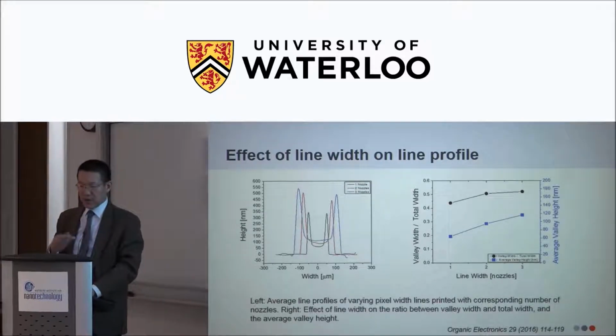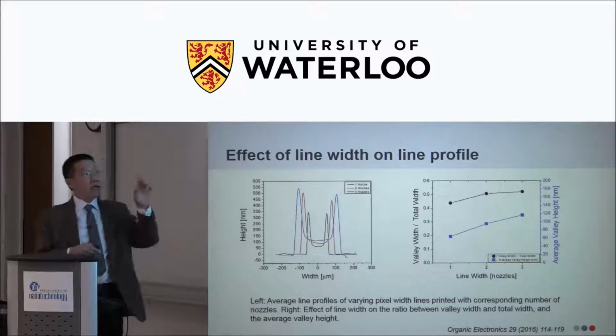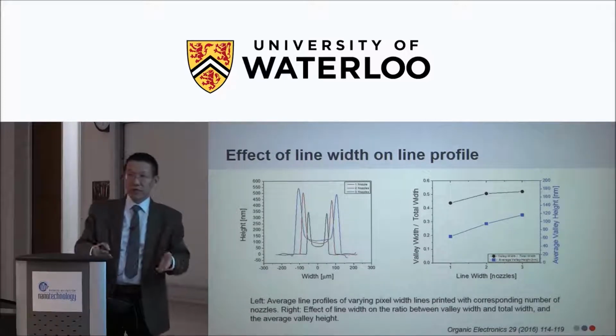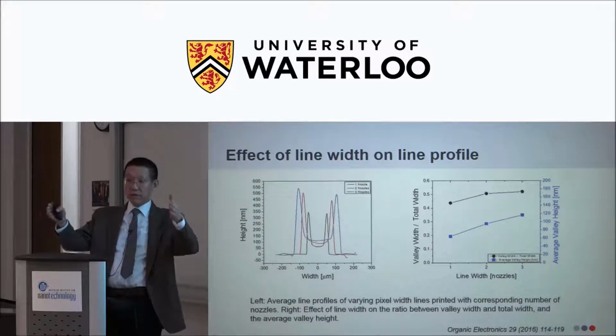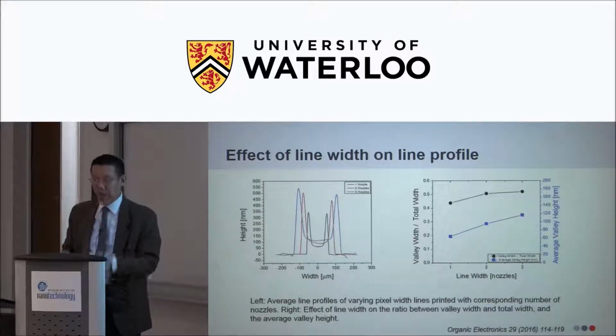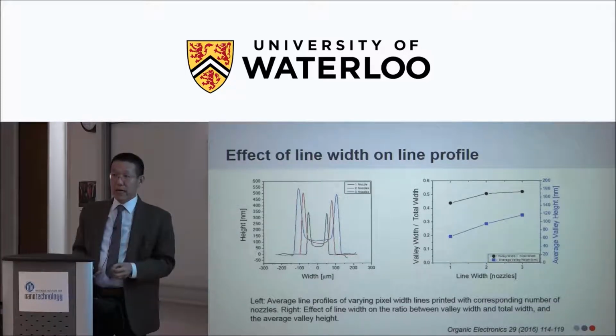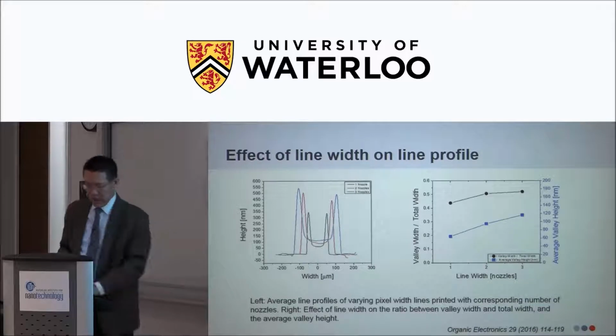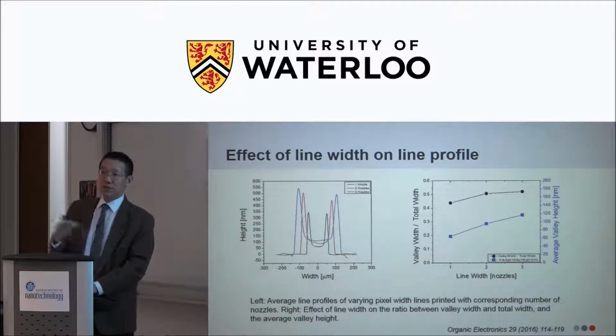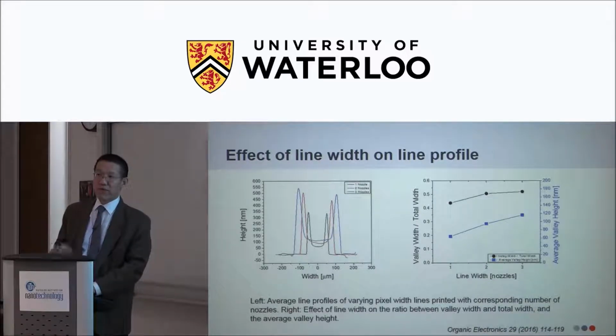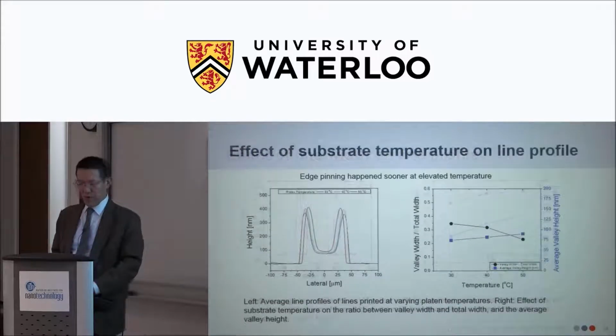And then by controlling temperature and how much material you dump onto the substrate, you can control the width of the flat area. Because of the lateral flow, our transistor yield actually increased dramatically, because you don't face the pinhole issue anymore. Okay.